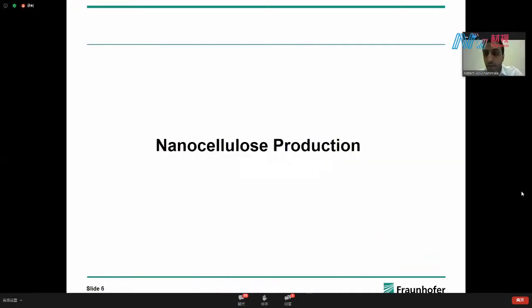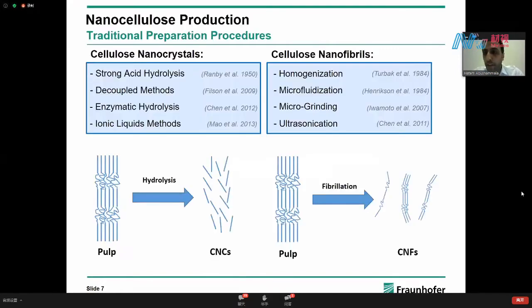Now I will give you a very fast idea about nanocellulose production, and I will not talk in detail about the processes because there are different processes for making nanocellulose. But overall, for cellulose nanocrystals, the standard method is strong acid hydrolysis, mainly with sulfuric acid. In such a process, the amorphous regions of cellulose are dissolved through hydrolysis by the protons of the acids, and the cellulose crystallites are liberated in the form of cellulose nanocrystals. For making cellulose nanofibers, usually the pulp fibers are mechanically fibrillated using a wide range of techniques such as homogenization, microfluidization, and microgrinding. Most of these methods apply strong shear forces on the pulp fibers to make these cellulose nanofibrils.